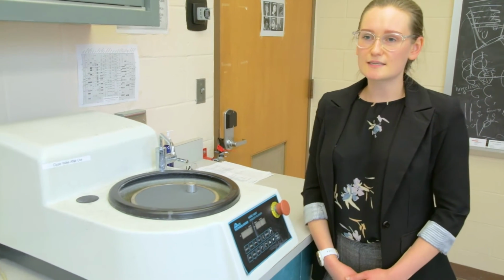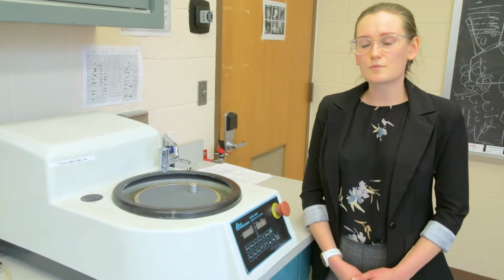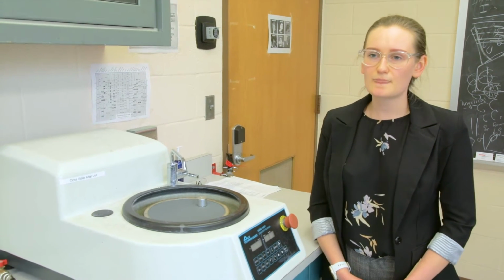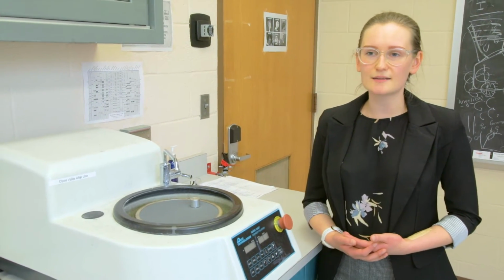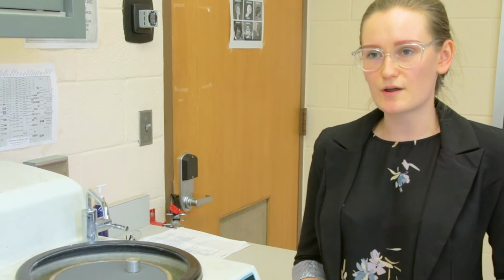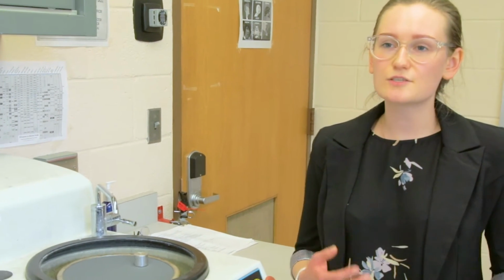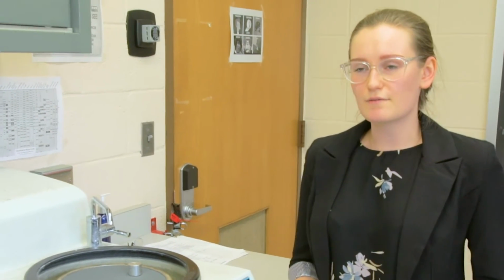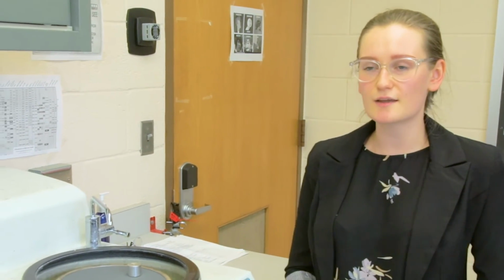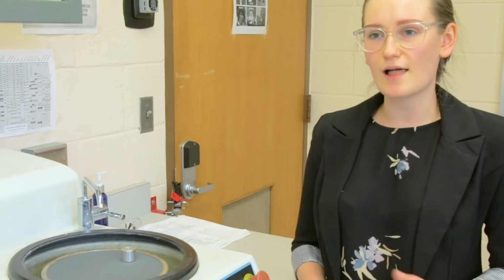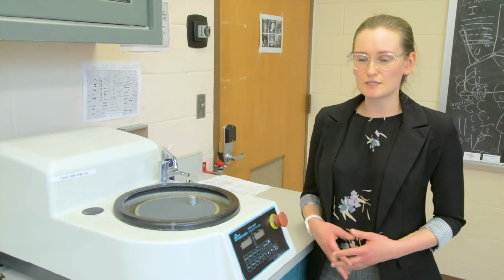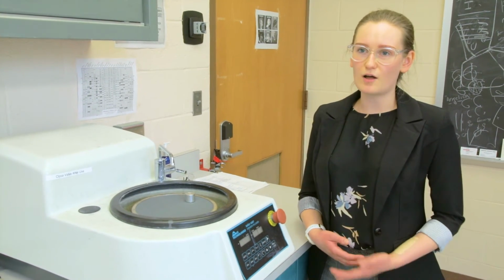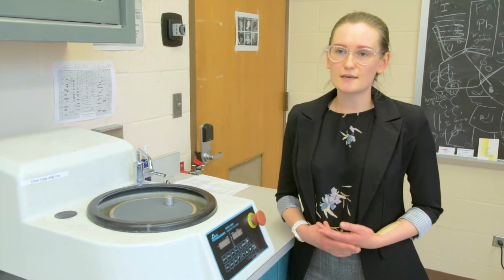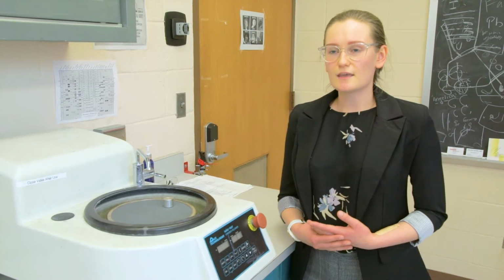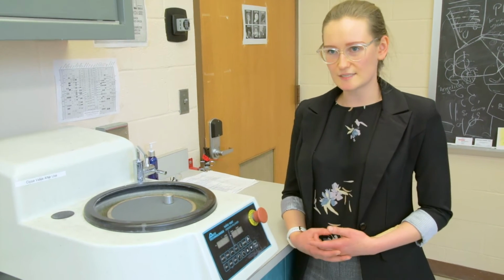These samples are then sent to the Argonne National Lab, where we use their IVEM microscope, which allows us to irradiate the samples with ions and observe in situ what is going on in the transmission electron microscope. This allows us to follow the microstructural evolutionary changes in the alloys during irradiation. The goal of this project is to observe the radiation resistance of high entropy alloys in regard to their chemical composition and the elements involved, and what role each element plays in assisting or not assisting the high entropy alloys in their radiation resistance.